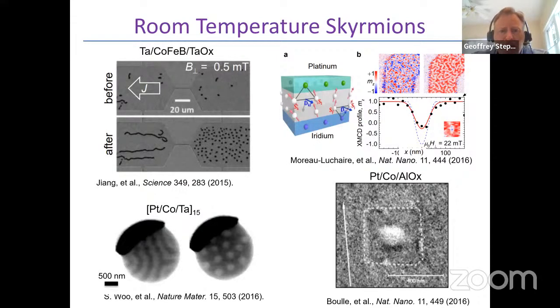And the idea behind these kinds of structures is that by taking a ferromagnet and embedding it between two dissimilar materials, you build in a broken inversion symmetry. And by tuning those materials, one can amplify both the DMI and the spin orbit torques that can be used to control or drive spin textures in these materials as well.